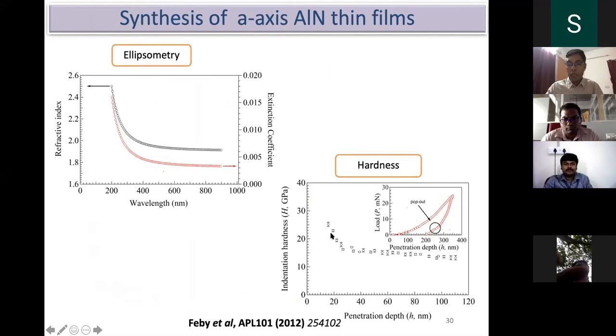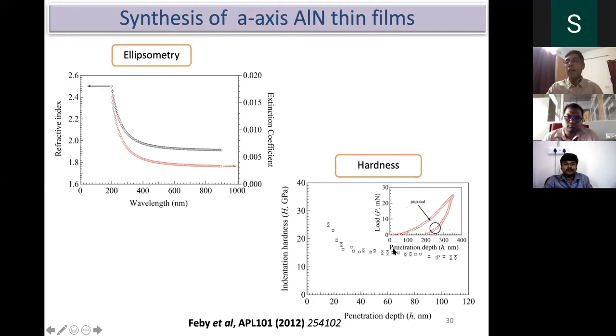When we tested the hardness with depth, because the thickness of the coating is very small, the hardness roughly stopped at around 19 GPa. Amorphous aluminum nitride showed 18 GPa, and the crystalline one decreased because of different annealing temperatures. And in the case of a-axis-oriented aluminum nitride, it's 19. So you can understand that aluminum nitride can show anywhere between 15 to 20 GPa hardness.